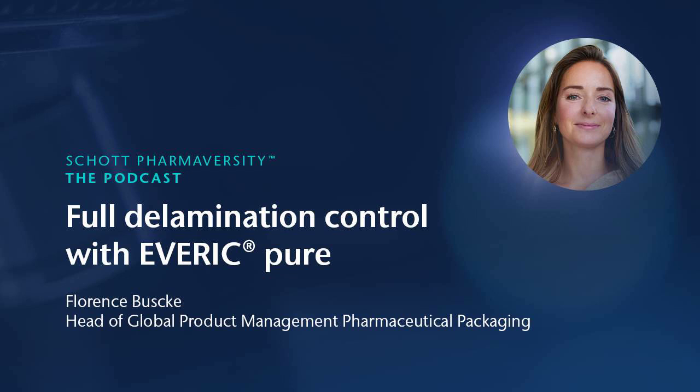So all in all, if we talk about the root cause of the delamination, and we talk containers here today and what the influence of the container is, we have a root cause that is well known today. The principle is simple, if I can say so by explanation. Volatile components like the boron and the sodium evaporate from the glass bottom and form an inhomogeneous microzone in this near bottom area. So you have this delamination zone, which is a local zone, as I said, that is critical to phase separation. And phase separation means, due to this boron and sodium insertion, you can later have this issue that I described at the beginning as a result of local corrosion.